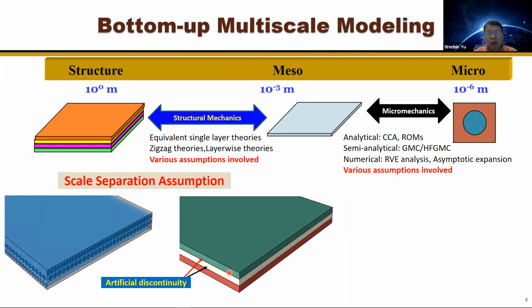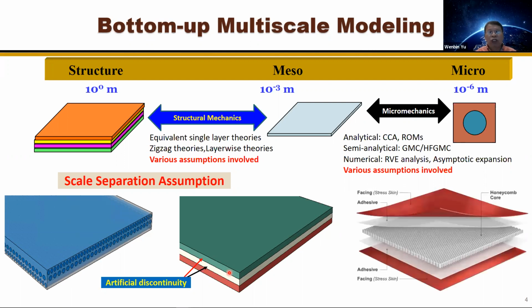But when you go to damage and failure, because damage failure is a local phenomenon, then we have difficulty having a good prediction. And also for some situations, even the global behavior will be wrong. For example, we have a honeycomb in the middle, a sandwich structure with face sheet in terms of laminate. Then the traditional way, what we do is that if we use the bottom-up multiscale modeling, we take a unit cell,